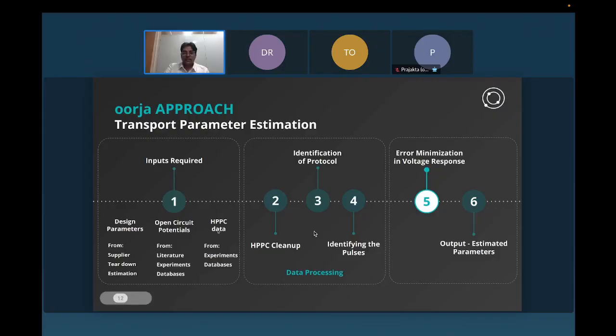Now, HPPC data can be obtained by conducting experiments on the cells that are going to be used, or there are sometimes databases where you have HPPC tests conducted. But we would always recommend conducting the experiments on the particular cell you are interested in modeling, because whatever databases we have may not be an accurate representation for the cells that you are trying to model. Now, one of the challenges with any experimental data is that the data comes with a lot of noise because of either the sensor measurements or something happening during the experiment itself.